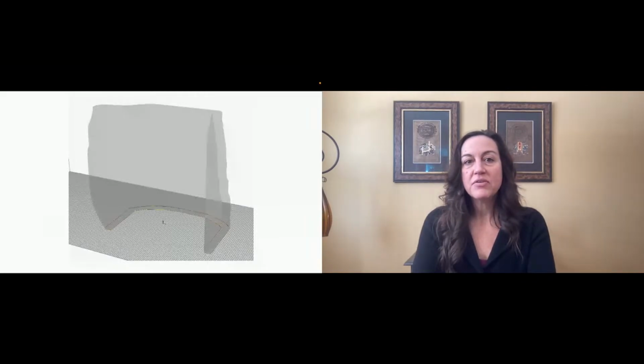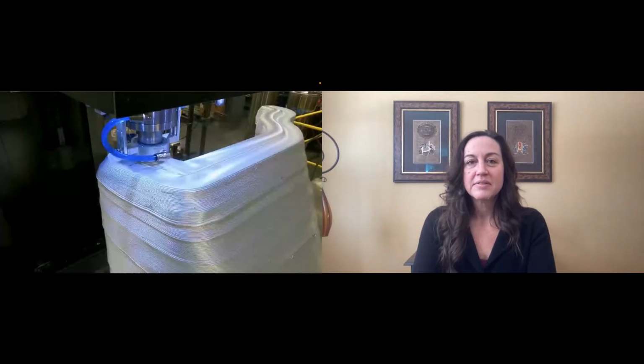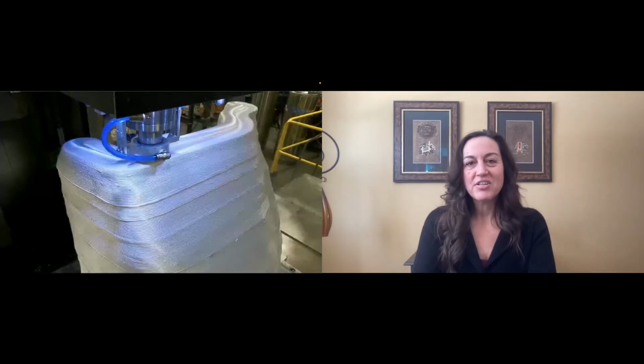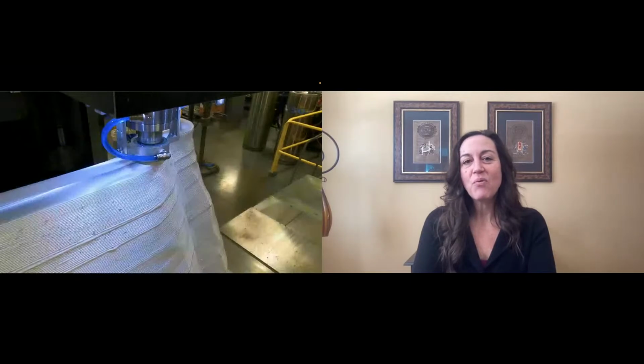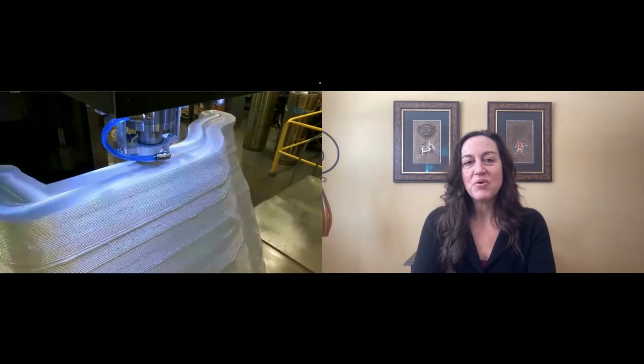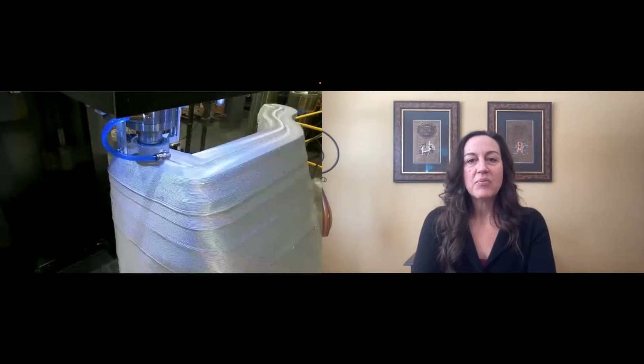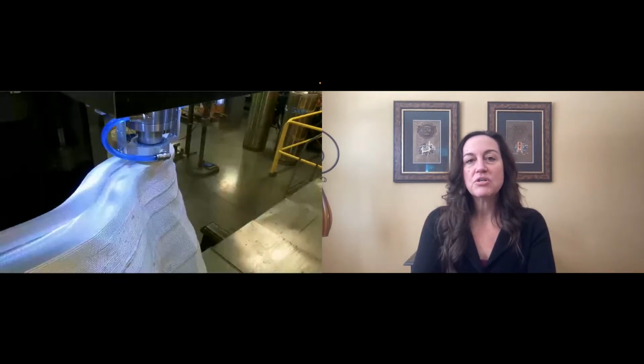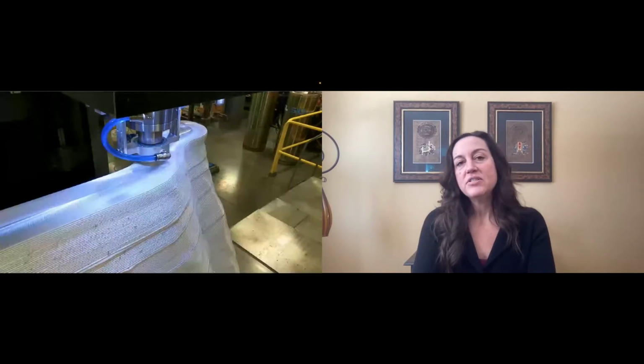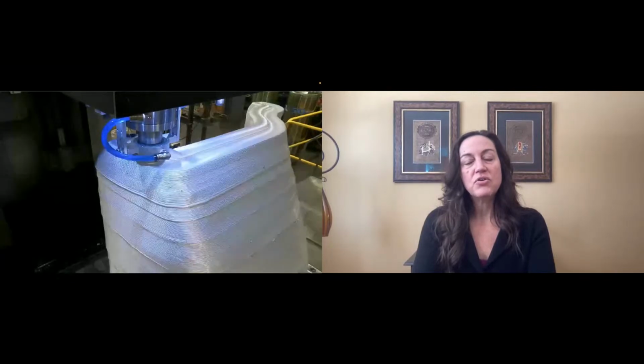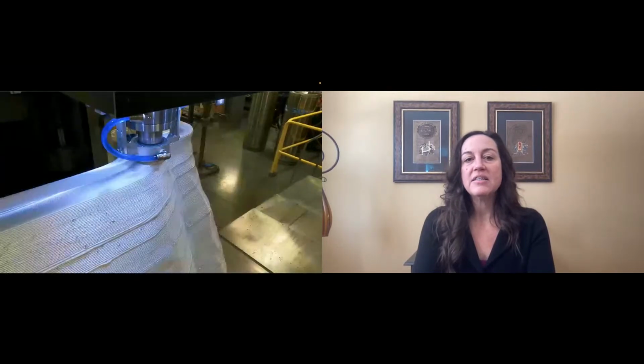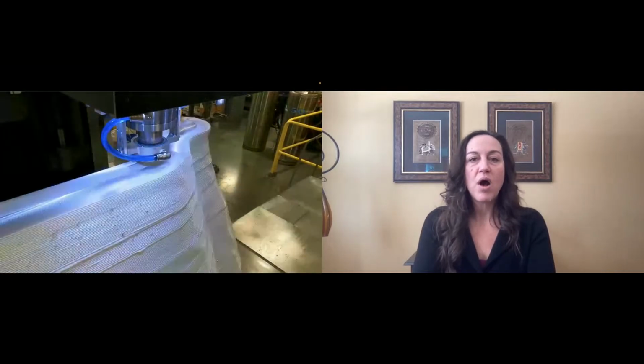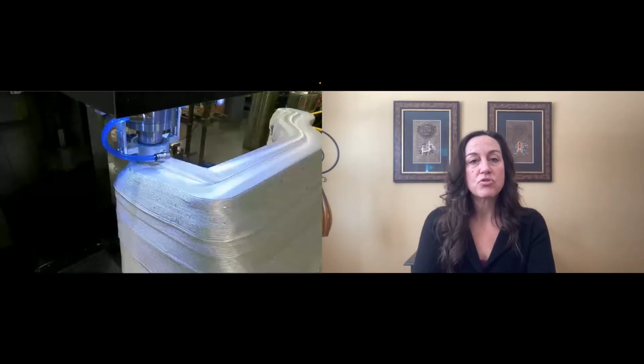And what that looks like in reality is this. And so this is a great demonstration of how you can build even bigger wall thicknesses with the ability to do overlapping tracks. This is something that we would have tested out at our facility, determined how much overlap is needed, and then done some analysis just like we looked at to verify that the material in that overlap area has the same quality as the material of a single track wall.